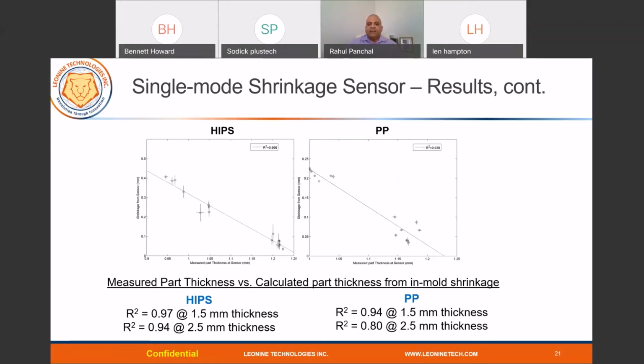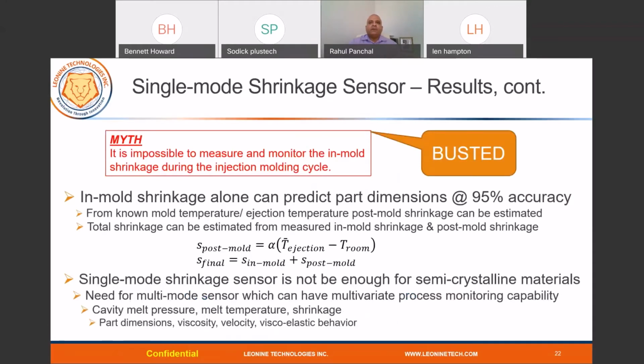But ultimately, one of the goals, to measure the in-mold shrinkage, was successful. There was a myth that you cannot measure the in-mold shrinkage during the molding cycle. Even though it has a 97% correlation for the HIPS and 95% for the polypropylene at the smaller thickness, we still think that for semi-crystalline or certain materials, the single mold shrinkage sensor is not enough. It needs to measure more than just shrinkage. So that's where all the brainstorming started.